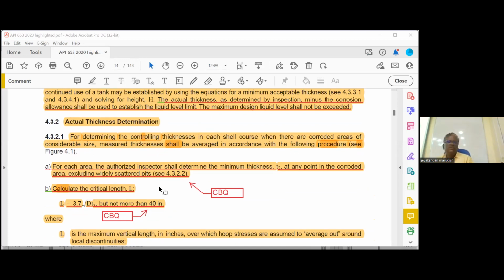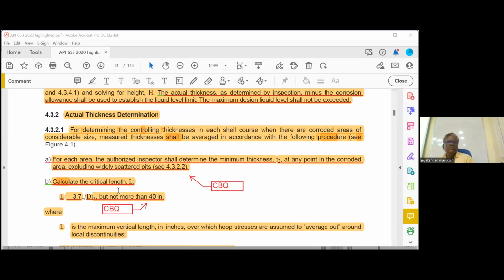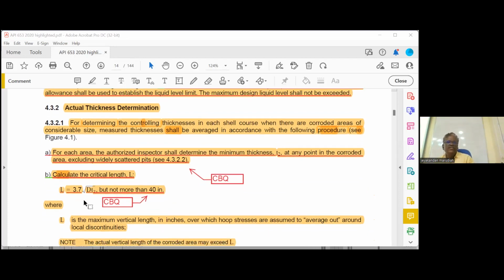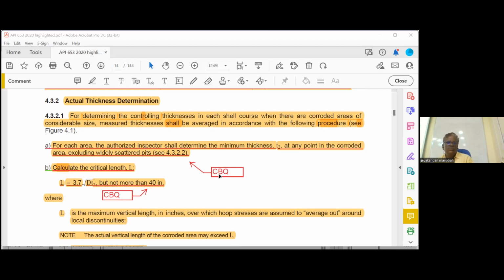Highlight that one. A, for each area, the authorized inspector shall determine the minimum thickness T2 at any point in the corroded area, excluding the scattered pits. Pits you should not consider. Okay, next, calculate the critical length L. L is equal to 3.7 square root of DT2, but not more than 40 inch. This we already completed. That is a closed book question.